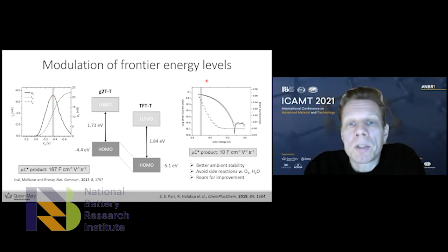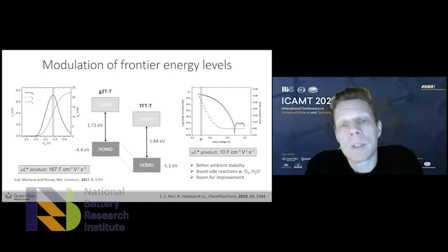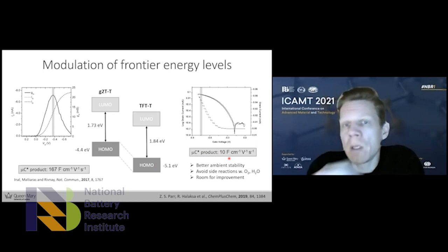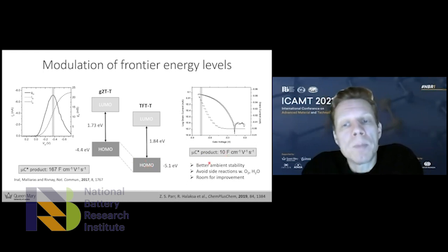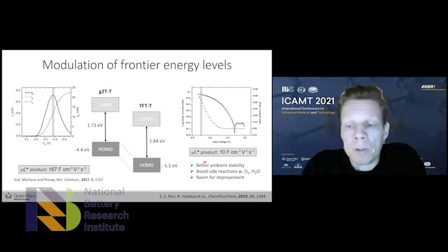Our new material with the tetrafluorobenzene, due to the much lower HOMO level, the increased ionization potential, we need to bias the material higher to get a peak transconductance. So we need to apply a higher bias to get this sensor to work. And also we see a significantly lower mu-c star product, at least an order of magnitude lower. The lower HOMO value does mean that we have better ambient stability. It's less likely to react in an oxidative way with ambient species such as oxygen and water, but there's definitely room for improvement in terms of the performance and also the energy levels.